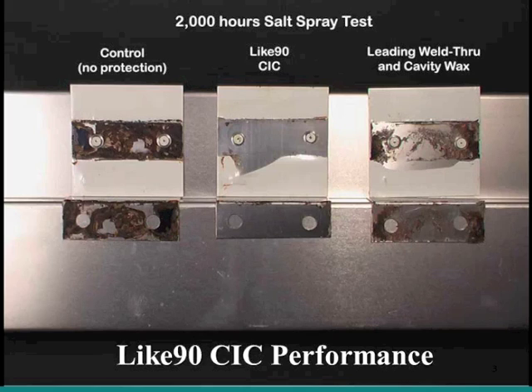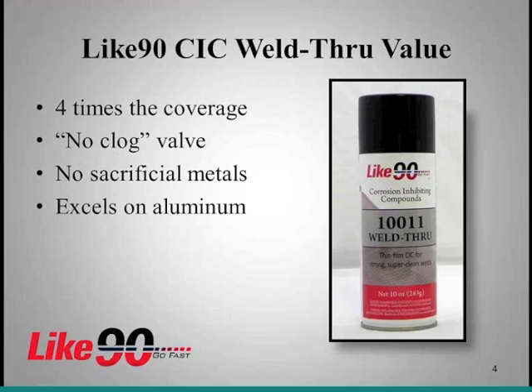So that way, when you're done welding, most of the time when you weld, you're going to get a little burn back around the inside of the panel. And with your typical weld-through primers, the zinc and coppers are sitting on that bare metal, and you basically have corrosion starting day one. Now with ours, you get 4 times the coverage with the weld-through product. So no clogged valve.